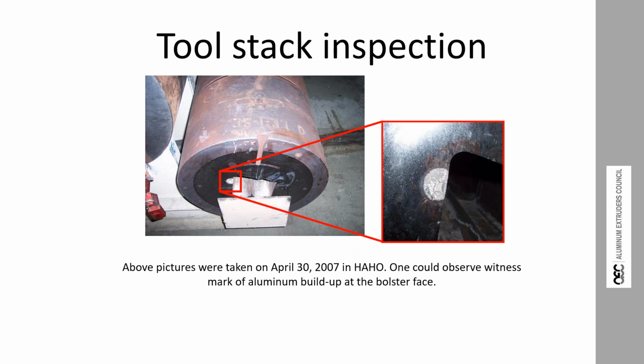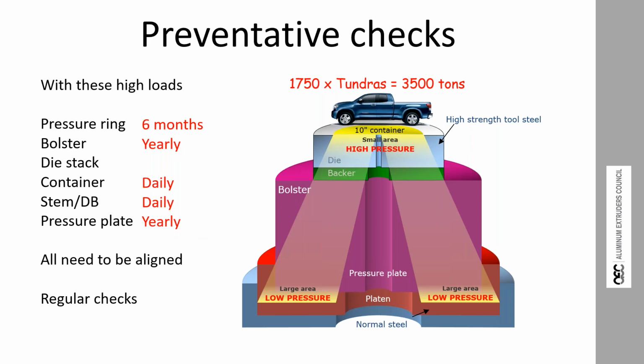And that led us to do an audit of the remaining bolsters to find out how many were perfectly flat, how many were perfectly parallel, were they in tolerance and dimensions. And we ended up having to buy some new bolsters. But it did improve our die life and our production. So, preventative checks. And I refer you to the webinar on the AEC library, which Chris Jarrett and I did a few years ago now. We did a webinar specifically on just alignment, so I'm not going to beat too much of this. But the recommendation was the pressure ring in the platen should be checked for flatness every 6 months, and you should have a tolerance. And Al Kennedy on his website has all sorts of numbers about what these tolerances should be.